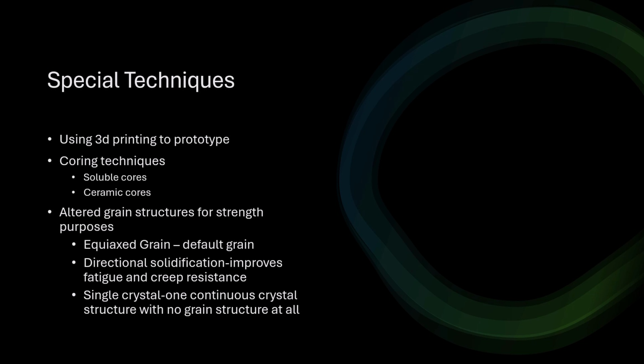To create features like internal channels or cooling passages, foundries use ceramic or soluble cores. Soluble cores are made of water-soluble wax or polymers. They're inserted into the die and wax is injected around them. Afterward, the core is dissolved before the shell is built. Ceramic cores are more durable and can handle complex high-temperature applications. These are left in place during casting and removed afterward with a chemical bath or high-pressure process.